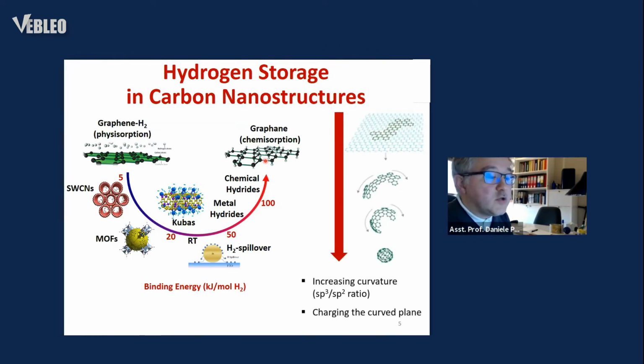Hence, it's necessary to tune the binding energy in the suitable range of 20-50 kJ per mole to have hydrogen absorption desorption close to room temperature. And it was theoretically proposed that there could exist several strategies to reach this target. In particular, in case of carbon systems, it has been proposed that besides more exotic strategies difficult to realize, it can be obtained simply by both curving the graphene plane and charging the curved carbon.